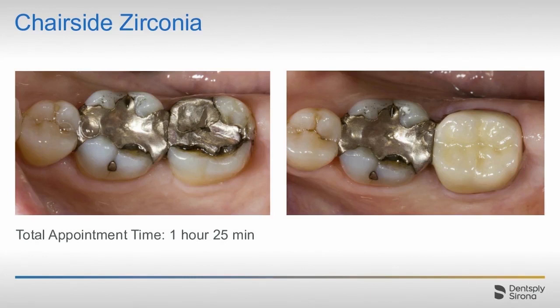So I think this result is quite good, specifically for a second molar. It's a little bit opalescent, a little bit opaque. That's just the nature of high-strength zirconia. But what it does is this appointment was done start to finish in 1 hour and 25 minutes. Now, at the very end of the presentation, we'll talk a little bit about time. And my goal with every chairside restoration is 1.5 hours. If I can kind of keep it below that, I'm quite pleased.